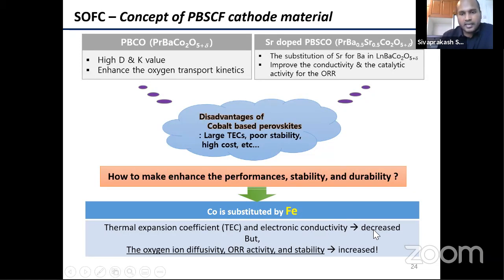Although it decreases the electrical conductivity, it is still enough for current collection in the fuel cells. The second advantage is that oxygen diffusion and oxygen reduction reaction stability was increased by doping iron on the cobalt side.